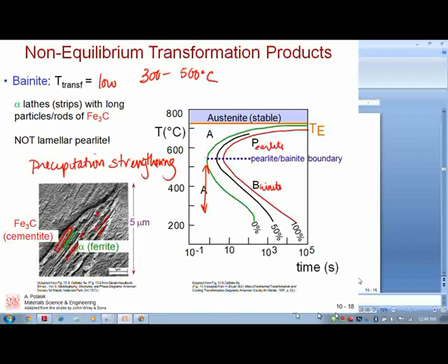So right in here, we might get some weird sections where pearlite, really, really fine pearlite forms, some where bainite formed. I mean, that's kind of outside the scope of this class. Really, I just want you to understand why we would get bainite instead of pearlite when pearlite is the equilibrium structure. That's the way it wants to form, the way it forms when we were talking about phase diagrams. We wouldn't get it if we inhibit diffusion enough. We're not going to allow that to happen because equilibrium requires slow enough cooling to allow for diffusion. So that's where that boundary is.